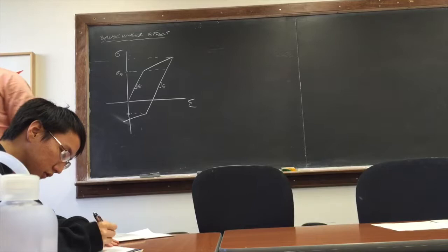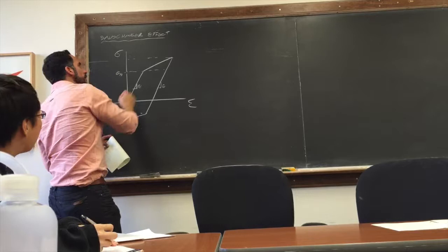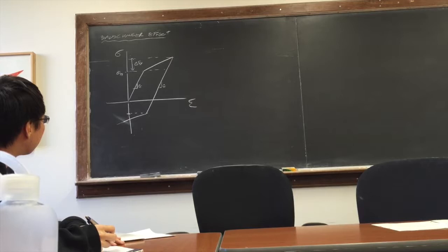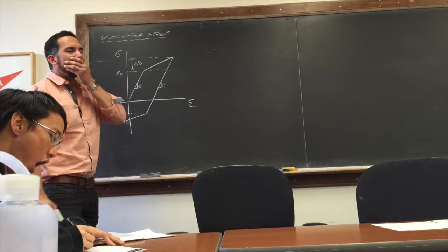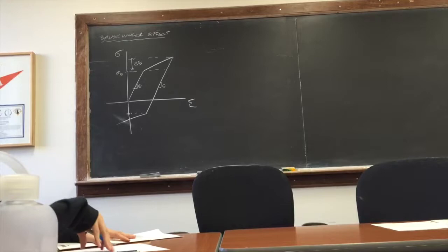Okay? And the same will be true for the tension part. So whatever we push down here on the strength, whatever change in the strength we've made, call it delta sigma y, will be penalized from whatever you had on the other side. Okay, so tension compression is not really important. Whatever you pull, you have to give up on the compression side and vice versa. The way I rationalize it is that there is a zero sum game in terms of strength. You either utilize it in tension or in compression, and that's it, okay?